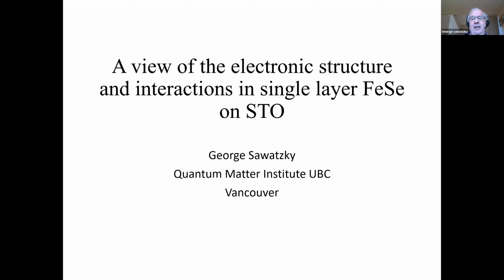So the single layer FeSe. Iron selenide itself, of course, is also a superconductor. It doesn't have a magnetic transition, so we all feel that this is a nice thing to study. The transition temperature of bulk iron selenide is very low, about 8 degrees Kelvin, if I remember correctly. It has a very low carrier density, a very low Fermi energy, and only electron pockets, and apparently no hole pockets in the single layer type material.